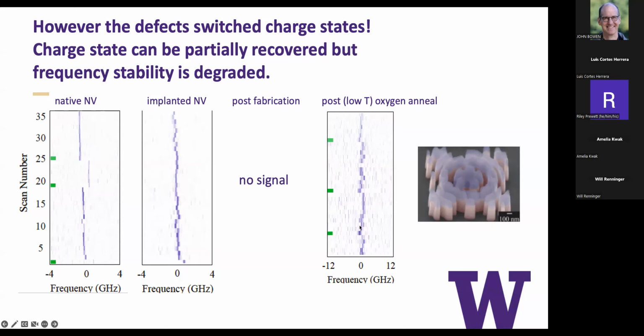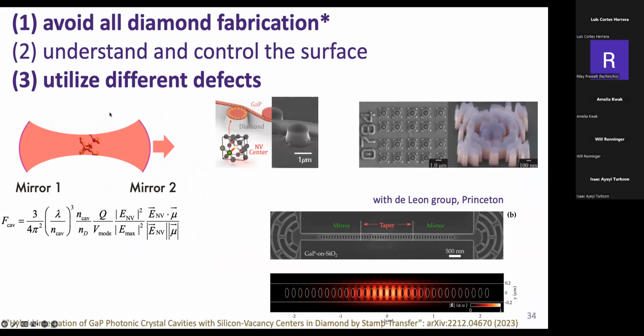We were able to bring it back somewhat, but you'll notice that I'm cheating here. The frequency is weaker, but then also the frequency range is different. So this is telling us we can't even expose the surface to a plasma without affecting it. And so where we are right now is we believe that for something like the NV center in particular, which is the most successful defect so far, you need to avoid all diamond fabrication. You want to, and people are still working on this, actively control the surface, get the defect how you want it to be, and then simply assemble your cavity structure onto the diamond surface.